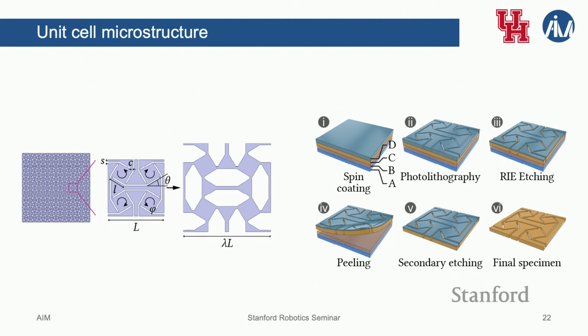The fabrication is, if you're familiar with clean room technology, very standard. We try to make it as standard as humanly possible so that we don't depend on any specialized techniques. So we spin coat 2 layers of polyimide, and then we spin coat a photoresist on top, and then we use a digital masking system to pattern the geometry, and then we etch down the grooves. And the only specialized step, number 4, is that we peel it off. Once we peel it off, we do a secondary etching, and then we get the final specimen. So you could replicate this in a day or 2 if you're familiar with clean room technology. It's really simple.